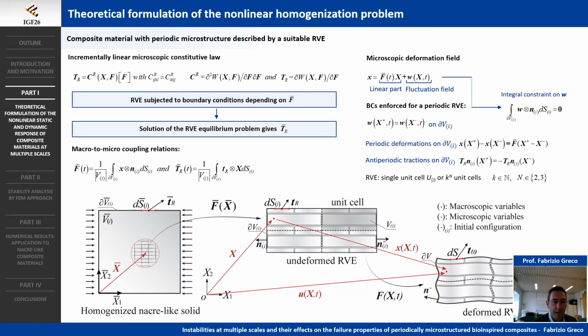The composite material analyzed here is assumed to have a periodic microstructure described by a suitable representative volume element, RVE. Each constituent is characterized by an incrementally linear constitutive law relating the rate of the deformation gradient tensor to the rate of the first Piola-Kirchhoff stress tensor in terms of the tangent moduli tensor. The RVE is subjected to boundary conditions depending on the macroscopic deformation gradient, and the solution of the corresponding nonlinear equilibrium problem for the microstructure gives the macroscopic first Piola-Kirchhoff stress.